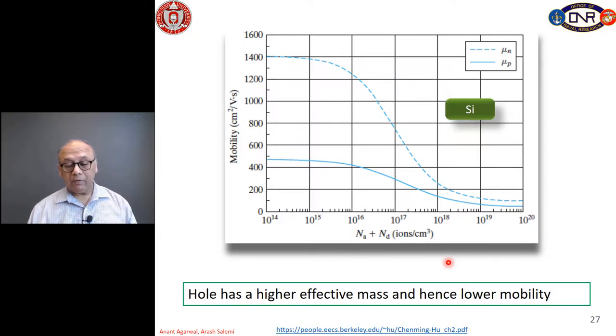In this chart, we are showing for silicon carefully measured electron and hole mobilities as a function of doping. And in this case, we have considered both acceptor and donor atoms if they are present at the same time in the semiconductor. So you can see that in general, as we increase the doping from left to right, the mobility of electrons and mobility of holes reduces quite a bit, and that's due to the impurity scattering phenomena.